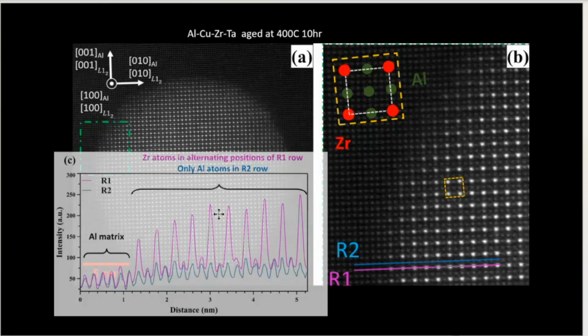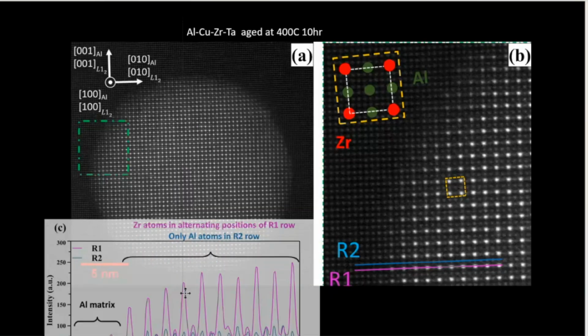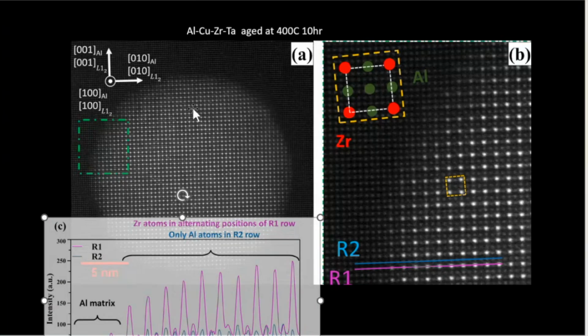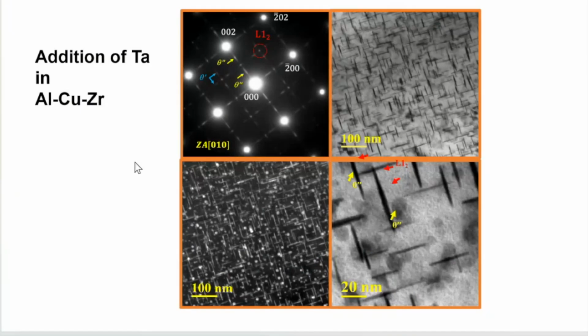At the top, you can see that Al3Zr is this ordered compound with the atomic columns clearly shown. If you look at the diffraction pattern after the heat treatment, you see that we actually get a very dense precipitate, and we get both theta double prime and theta prime together with L12 in the alloy. So tantalum additions actually enhance the distributions.